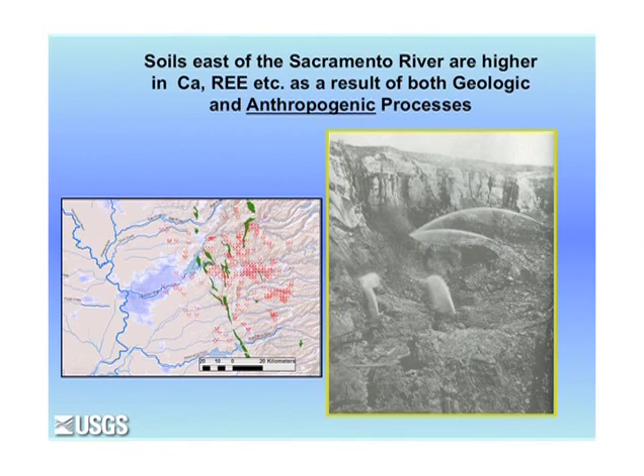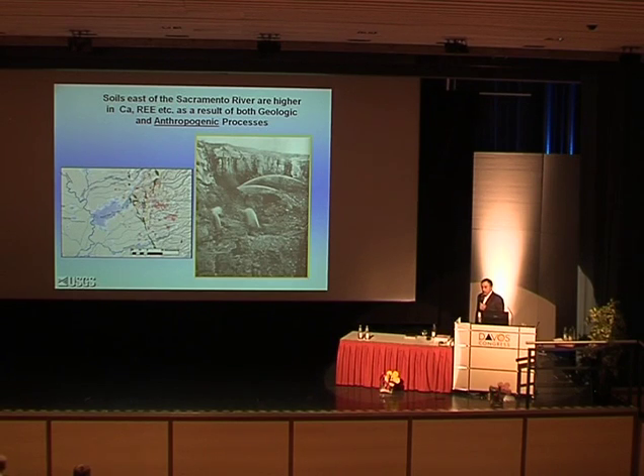Part of the gold was obtained from what's called placer mining or hydraulic mining. The miners would shoot high-speed jets of water against alluvial material that had some gold in it. The material would wash down. They'd separate the gold by density, and the rest of the material was just waste. Well, this waste, it was billions of tons. It inundated the Sacramento Valley, destroyed farms, basically stopped navigation on the Sacramento River. And so it was a huge issue. And ultimately, it was only stopped by a lawsuit. So anthropogenic processes have had an enormous impact on the eastern side of the valley.